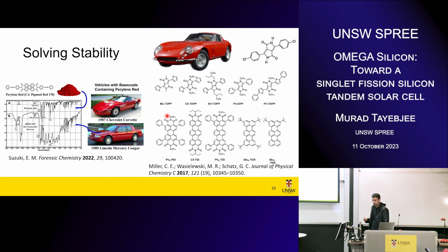Well, an easier way to think about this is the way triplets move through a crystal material anyway. The way a triplet goes from one molecule to the next is via tunneling, because there's essentially a potential barrier between each individual molecule, as there are no nuclei around. So it's tunneling from molecule to molecule. Then when it gets to something like silicon, my best understanding is that it will tunnel in concert in a process called Dexter transfer. And as soon as it's in silicon, that electron and hole don't know where they came from, because your dielectric constant's so large that they get screened from each other.